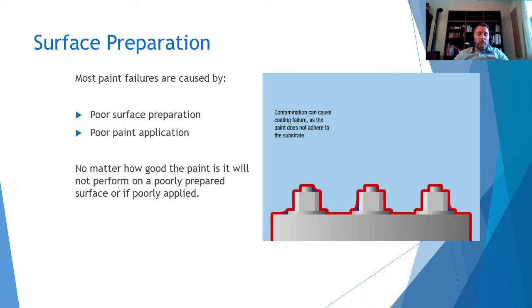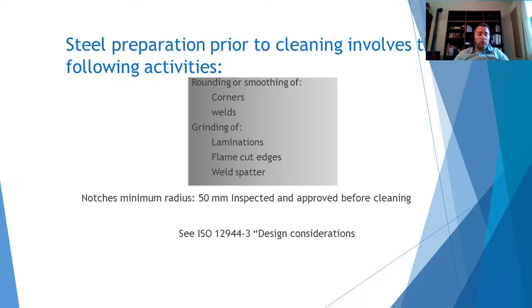For virtually every coating process, the first step, the initial surface cleaning and preparation, is the key step to the success of the coating system. Most paint failures are caused by poor surface preparation or poor paint application. No matter how good the paint is, it will not perform on a poorly prepared surface or if poorly applied. Steel preparation is the first and most important step prior to surface preparation, since modern coatings require both a clean and rough surface if they are to have long-term stability. The only exception is if they are specifically designed for application to poor surfaces, for example, surface tolerant coatings.